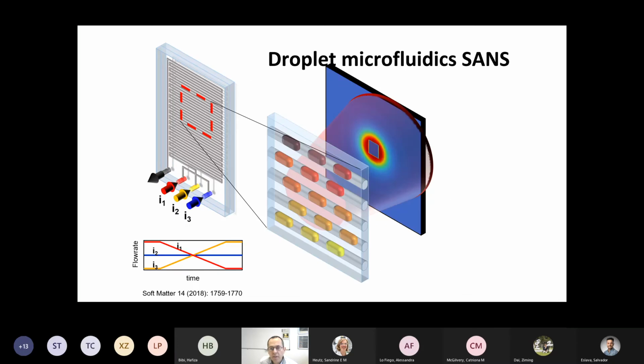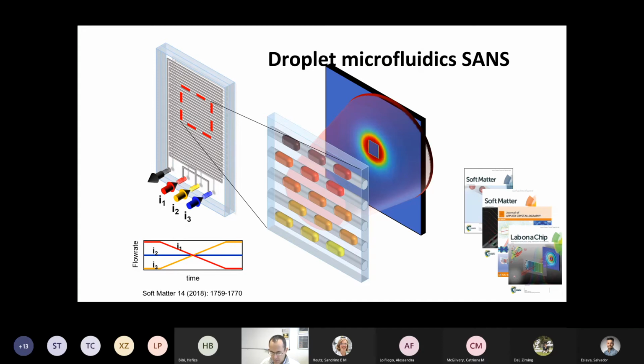Now connecting to the molecular scales in the last few minutes of this conversation, what we use for this is scattering. We can't really do high-resolution electron microscopies, because this process is highly dynamic. We need to arrest the particles, their center of mass. And so we use instead scattering as a non-invasive tool, mainly neutron scattering or X-ray scattering. And we use, again, microfluidics, with the potential of allowing you to do these things on the fly, so you can formulate these in real time.